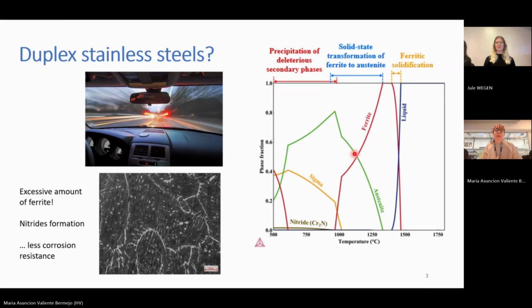So what happens when we have a very fast solidification? We have a huge amount of ferrite, the formation of these nitrides, and then the material is not so good for corrosion resistance as we wish.